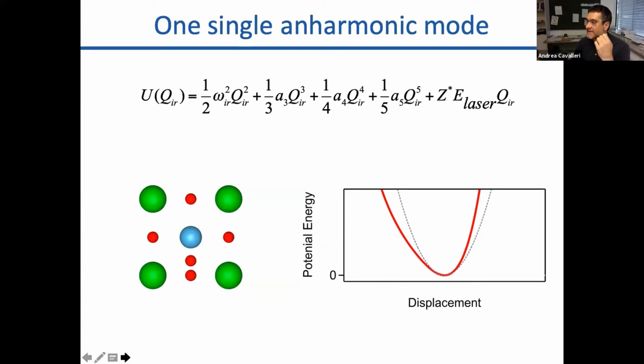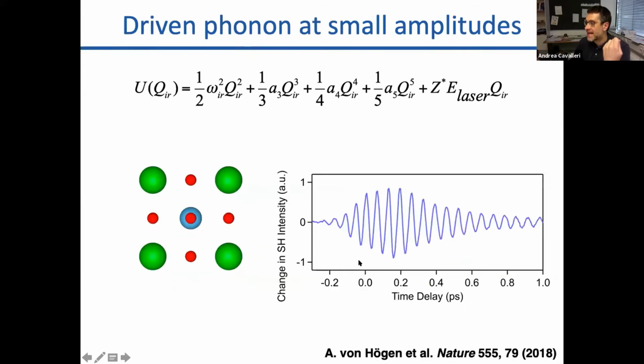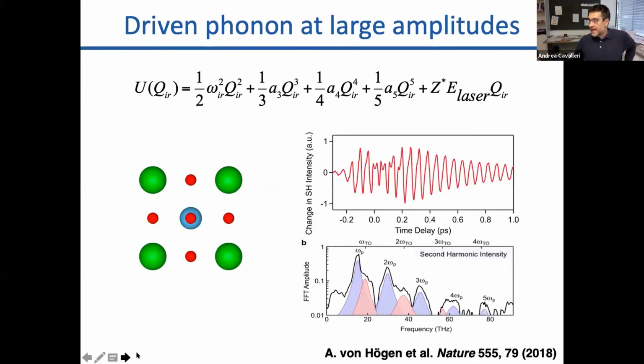And I can drive this mode to very large amplitudes, okay? When I look at this now in linear response, of course there's techniques where I can follow the response of this mode with a second laser pulse. And whilst at low excitation amplitudes, only the harmonic term of this energy is important, therefore I get a perfectly harmonic response. If I look at strong fields, I can get a very anharmonic response, which